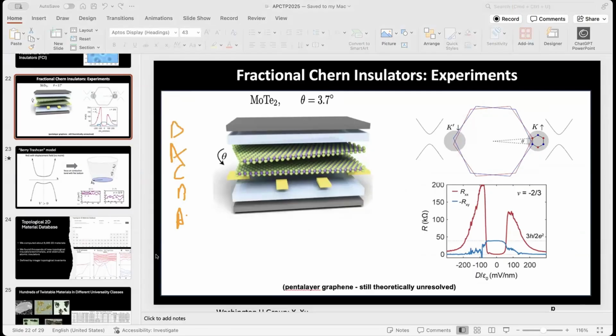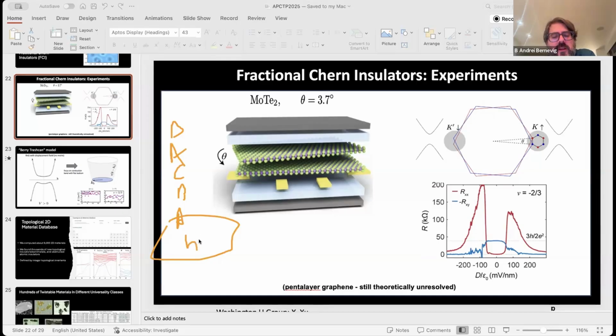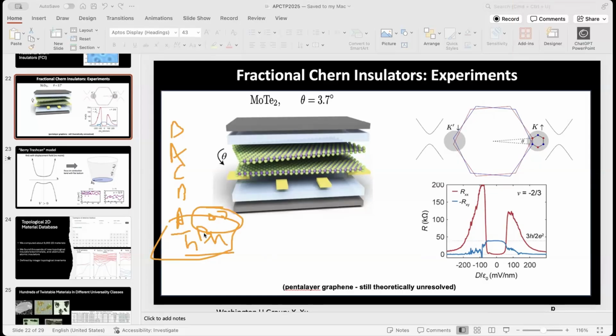AB, there's a twist with the boron nitride that is being done, about 0.7 degrees. Only when it's twisted and aligned do you see the fractional Chern insulator. Now, even if I didn't twist by 0.7 degrees, boron nitride would have a different lattice structure, so if I align it even at 0 degrees, you will get a Moire. The only difference is that if I have the same lattice, so graphene twisted, there is relaxation. Once you twist, the atoms don't like to sit in position, so they relax. The relaxation is a bit different when I twist versus just lattice mismatch with no twisting.